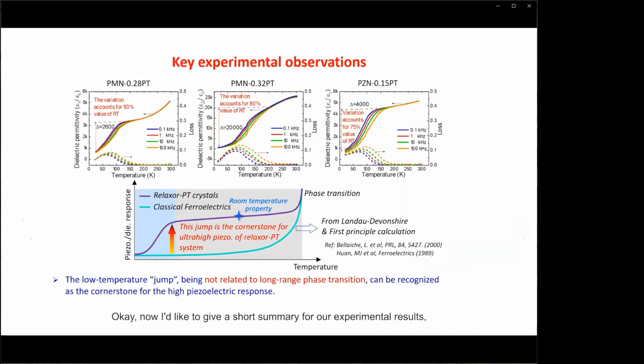Okay, now I'd like to give a short summary of our experimental results. We observed low-temperature dielectric relaxation behavior in relaxor lead titanate crystals. At low temperature, there is a very big jump of dielectric permittivity for Relaxor-PT crystals, and this jump isn't associated with a phase transition. Compared to conventional ferroelectrics, this jump can be recognized as a cornerstone for the high piezoelectric response of Relaxor-PT crystals at room temperature. In the following, I will use phase field simulation to analyze the mechanism for this phenomenon.